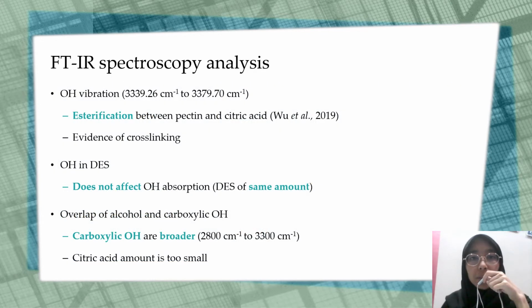OH vibration become less intense due to more esterification between pectin and citric acid, so there were less free OH groups. Since DES was of the same amount, its OH did not affect the absorption. There may also be an overlap of alcohol OH from ethylene glycol and carboxylic OH because carboxylic OH was supposed to be broader, but the amount of citric acid was too small to dominate.